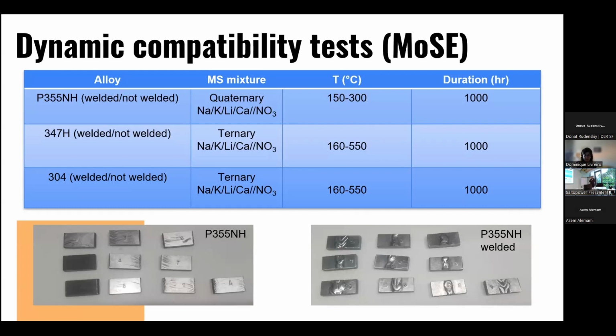These are some tests that are ongoing now in the MOSE facility. We decided to test the same steels at a higher TRL inside the MOSE facility. Here I reported the steels that we chose and the temperature that we are going to use, simulating the temperature cycling during an actual CSP plant. And we decided also to test the steel like this and the welded one, because we know that the welded one could be weaker, especially in proximity of the weld line.